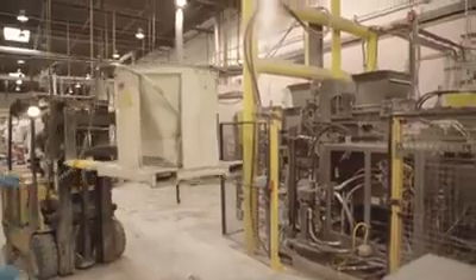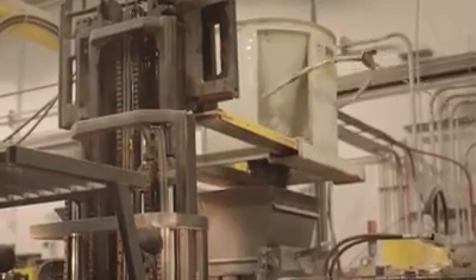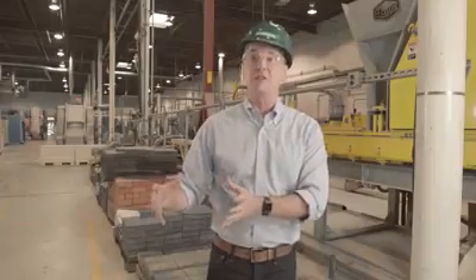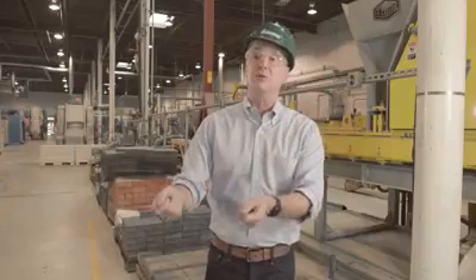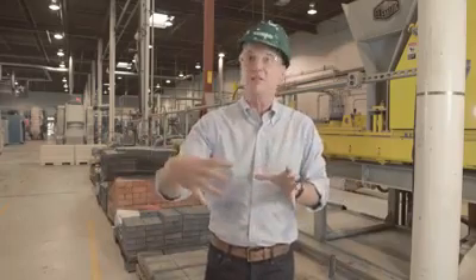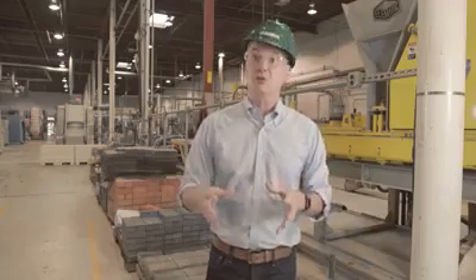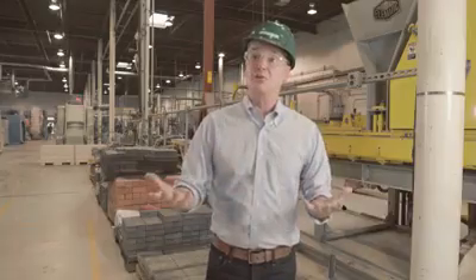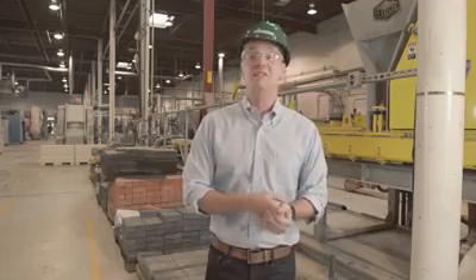For concrete, we use exactly the same raw materials, the aggregate, the sand, the water, all the admixtures, and the cement. We just change their cement out for our cement. We'll run exactly the same conditions in the properties, but then instead of putting it into a chamber with steam to help accelerate the cure, we actually have a chamber filled with CO2. And as we get rid of the water, the CO2 rushes in and becomes solid. You'll actually see the paver pick up about 5% weight, and that's the CO2 converting to essentially limestone, back to its original state. And so we've got CO2 that is permanently sequestered in that concrete and it's never coming out.